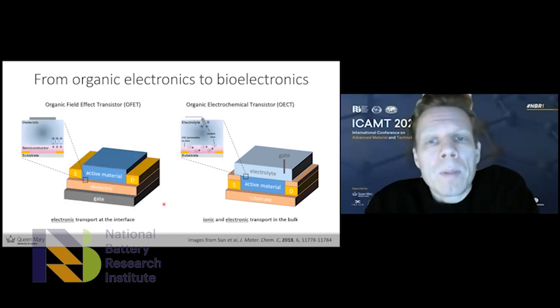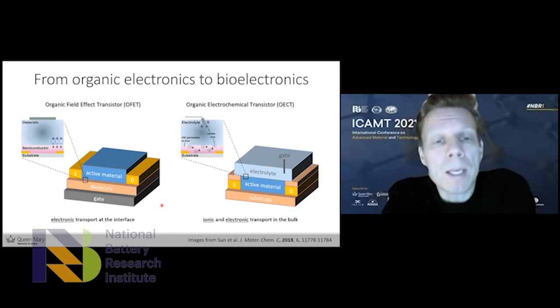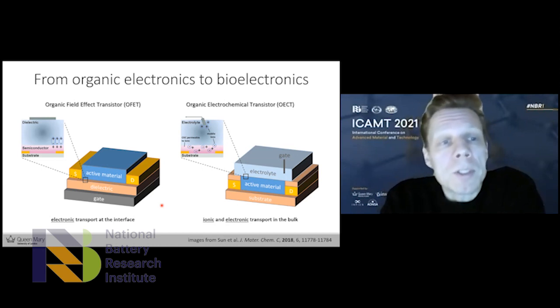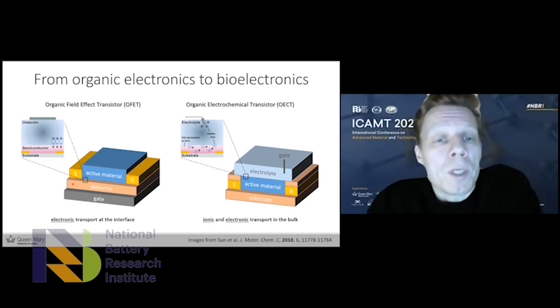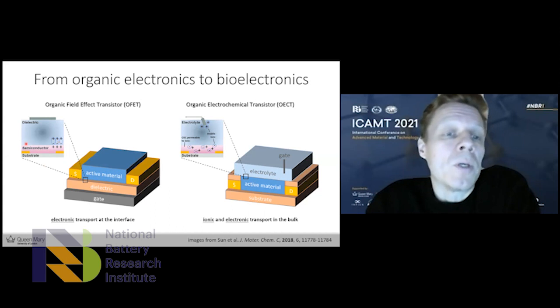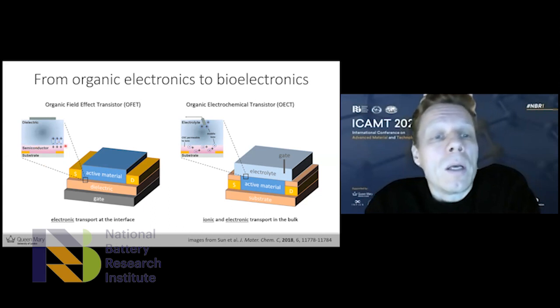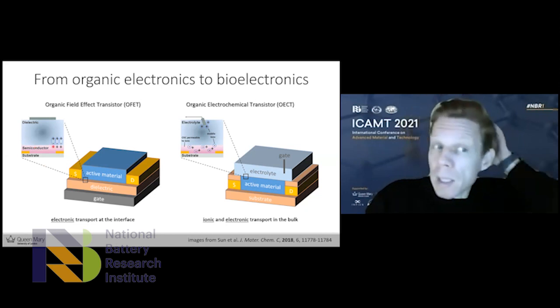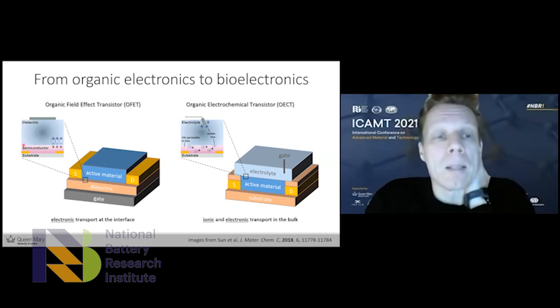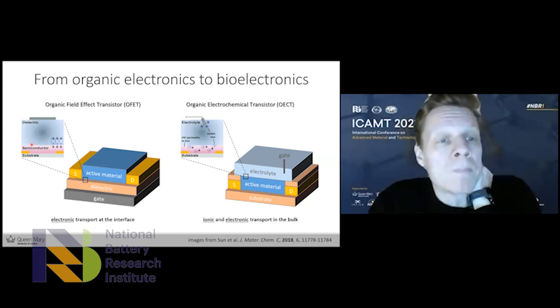And if we look a little bit more carefully at the operating mechanism of these types of transistors, you might be more familiar with the organic field effect transistor, which I've shown here on the left, where you have a solid dielectric, and how that operates is that you only build up a small accumulation layer between the dielectric, at the interface between the dielectric and the semiconductor, and all the charge transport takes place in a few monolayers very